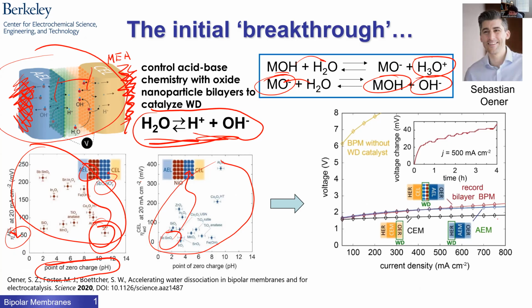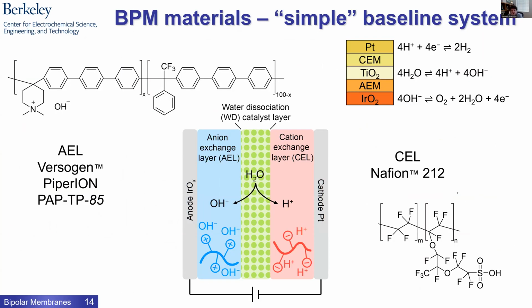And so this is just some early data showing that we can run our bipolar membranes at roughly 5 to 10 times higher current density than the commercial systems, really without any significant loss in voltage. I'll explore this in more detail, but I just wanted to highlight this early.